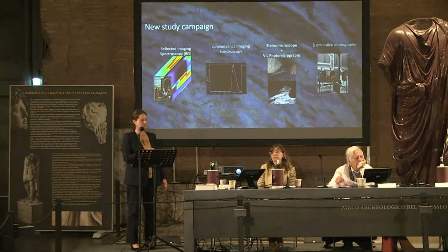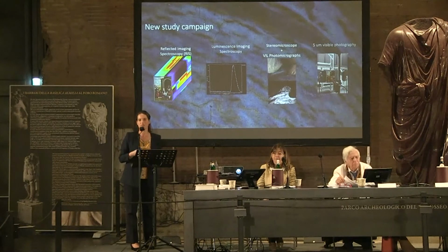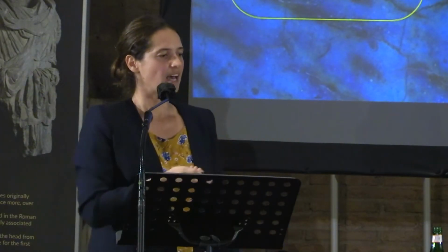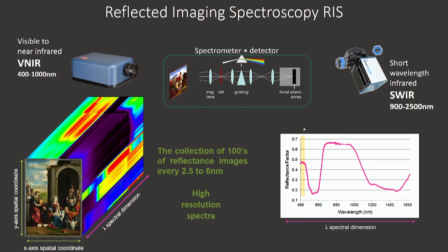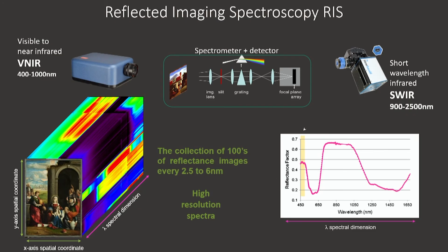It's usually, unfortunately, in storage. And this was a good time, not just because we were part of Bluenet, but because by this year the museum had acquired new analytical technique, so we could do a new study campaign. And we started with reflected imaging spectroscopy, which is a technique that collects light which is reflected or scattered by the elements composing the paint layers, and the outcome is a huge data cube that can be sourced for information, and the data cube has X and Y dimensions relating to the dimensions of your painting, and the third dimension relates to the spectral wavelength band collected, but it's a technique of spectroscopy, so we can also source a single pixel, get the spectrum and map it through the surface of the entire painting.